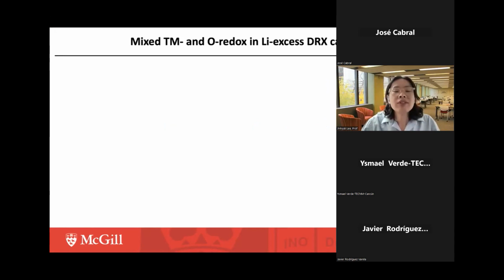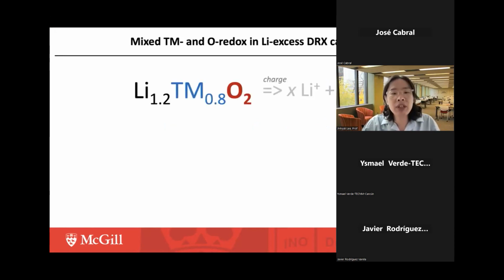So for example, let's imagine we have the composition of the lithium 1.2 transition metal 0.8 O2 composition. Now, from here, we can already know that there are nearly 50% more lithium compared to the transition metal in the structure. And now let's imagine we want to extract all these lithium ions from the structure to achieve high charging capacity.